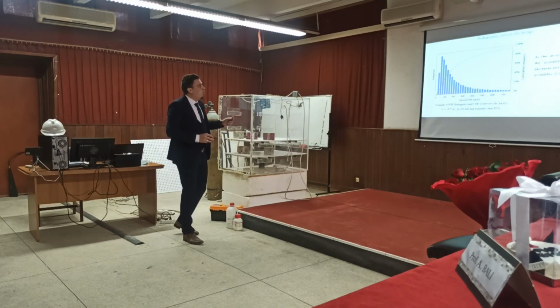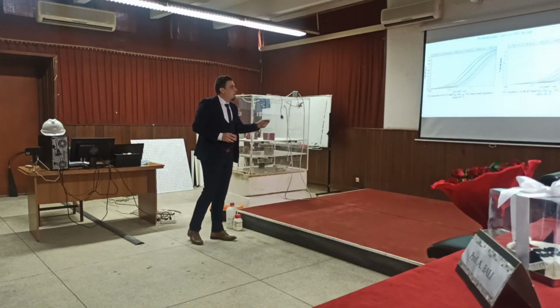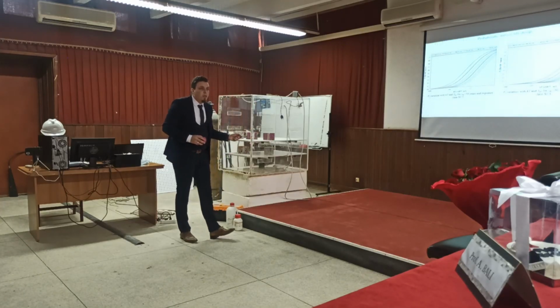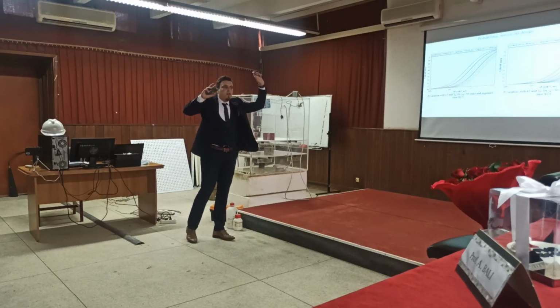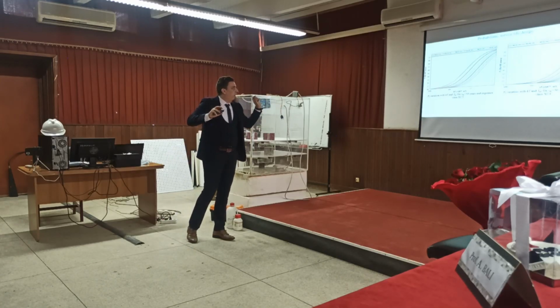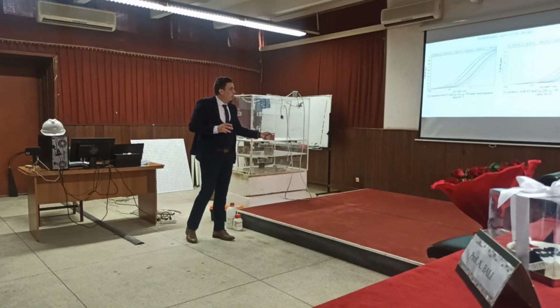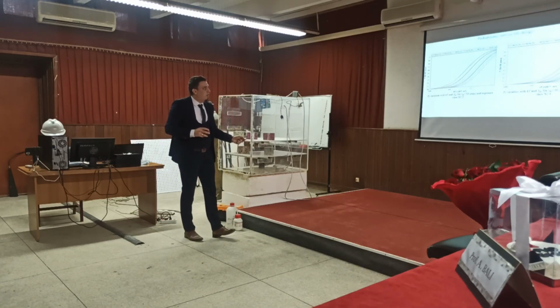After that, we developed these figures, which show the probability of failure as a function of KT for the 5 cover depths, for the 3 service lives, 50, 100, and 300 years, for both the XC3 and XC4 classes. This is an example for 50 years, this is for 100, and this is for 300.